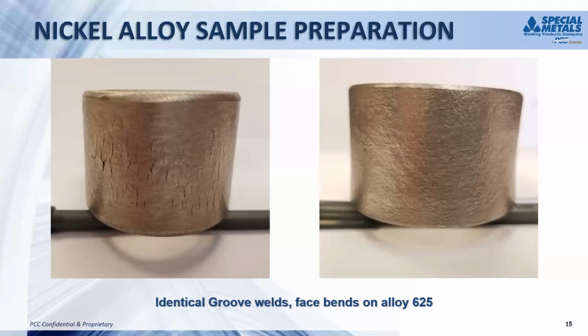However, with a nickel alloy, you're going to be limited to about 5 to 10 thousandths thickness per pass. If you don't do that, you run the risk of work hardening the surface of that nickel alloy. And what you get is a bend that looks like the one on the left, where it's completely cracked. They're very thin surface type defects, but they're very quick to fail a bend test. As you can see, that had pretty good sample prep. They did a nice radius on those corners to avoid problems there, but the whole surface was just cut with a CNC fly cutter at very high speeds, and work hardened just enough that when it bent, it just cracked.